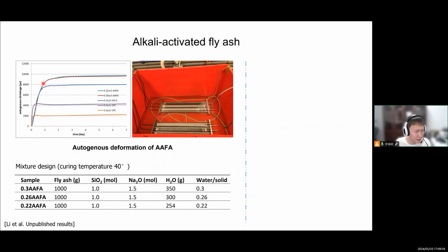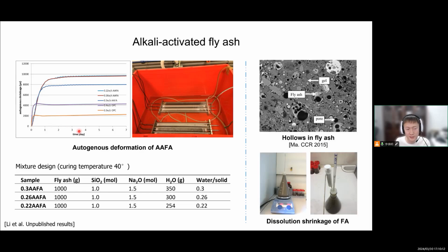People may think that with the early age shrinkage you see several thousand microstrain, so it can be large. Maybe the shrinkage is a very big problem, but actually not really, because this autogenous or chemical shrinkage in the very beginning is closely related to the hollow voids in the fly ash. During the production of fly ash, the temperature is very high, so there will be a very low air density, which is sealed in the fly ash particles, which are impermeable. So it's not permeable, so the air is sealed inside with a low air density.